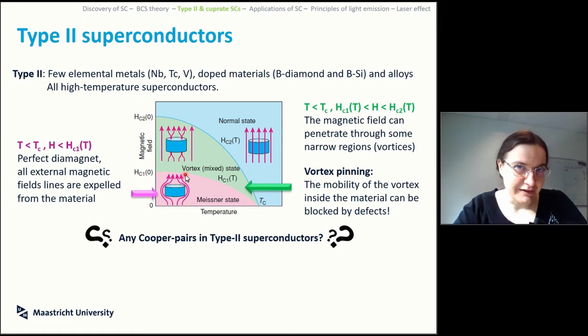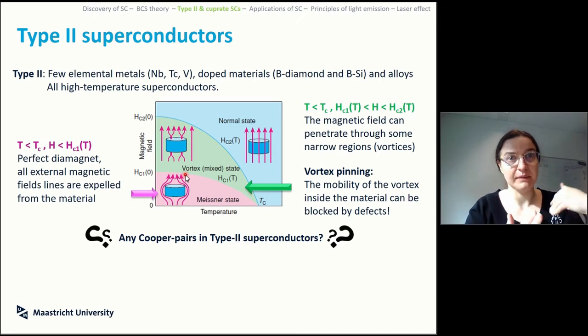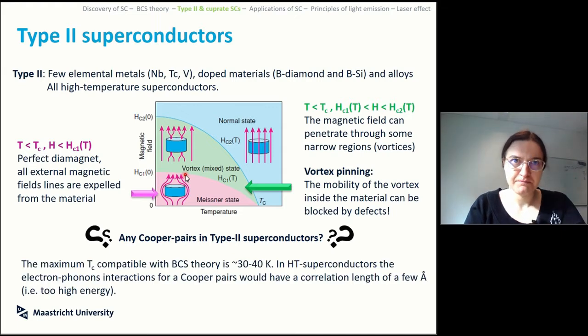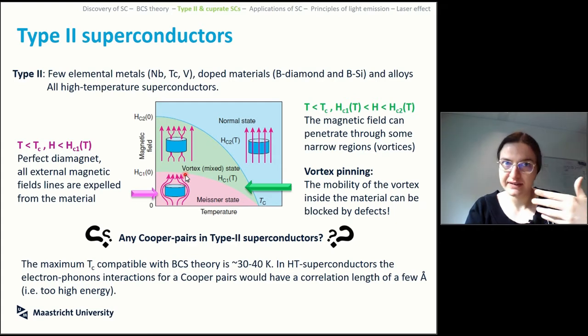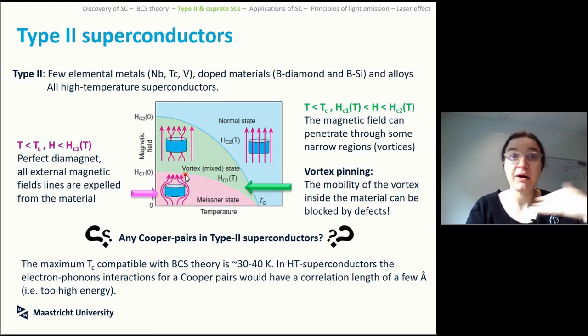So the big question here is, do you have Cooper pairs in this state? We've been discussing how the BCS theory of superconductivity explains how you have a superconductor: you create Cooper pairs below the critical field and below the critical temperature. Do you have the same here? This is a difficult question, because the BCS theory is proven, and thermodynamically and quantum mechanically sustainable, only up to about 40 Kelvin. When you throw in something like a high temperature superconductor that is superconductive at 100 Kelvin, this is way over the border of the BCS theory holding up.